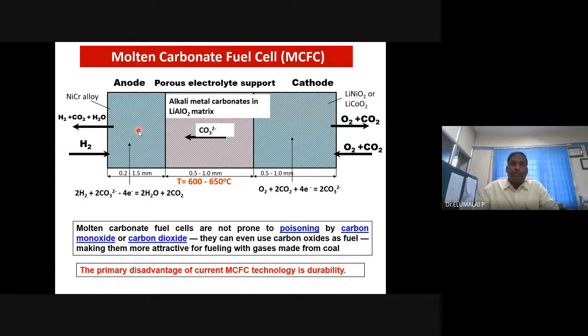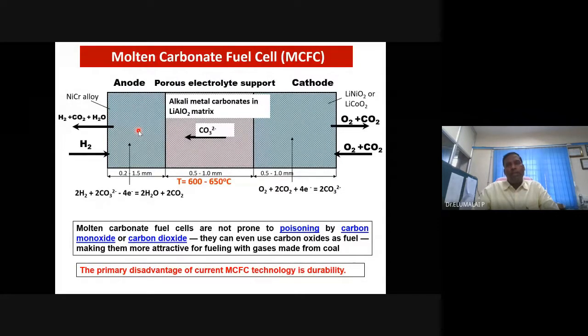Okay, let me complete. For the fuel, you can use hydrogen, or carbon monoxide itself can be used. Carbon monoxide itself can also be used as a fuel. If it is hydrogen, this is the oxidation reaction. Hydrogen is oxidized to water, and CO2 is reduced to carbonate, with oxygen being reduced. Same theoretical potential. So we have a carbonate based electrolyte, non-platinum or non-precious metals or metal oxides as anodes and cathodes. And the fuel choices are hydrogen, or carbon monoxide itself can be used as a fuel.